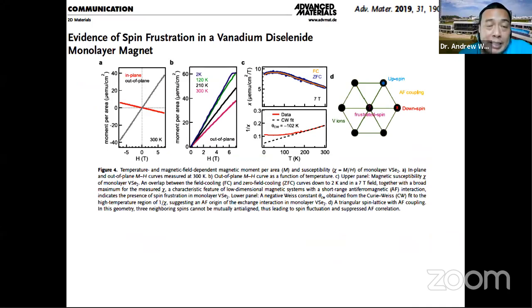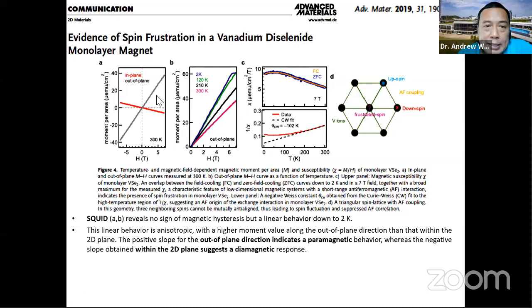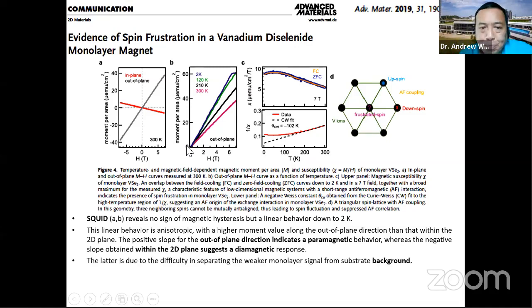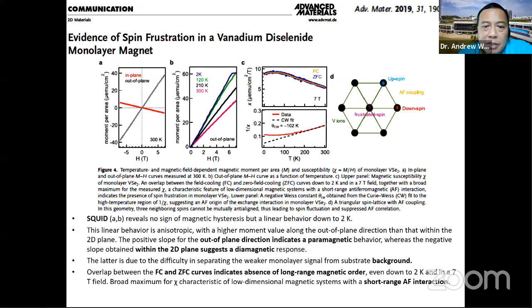So we did further bulk magnetic studies, and you can see that SQUID shows no magnetic hysteresis, but linear behavior down to 2 Kelvin. And it's a positive slope in the out-of-plane direction, indicating paramagnetic behavior, and a negative slope in-plane, indicating a diamagnetic response, which is probably due to the substrate background. And in the zero-field and field cooling curves, because they're similar, it suggests there's an absence of long-range magnetic order down to 2 Kelvin and 7 Tesla.